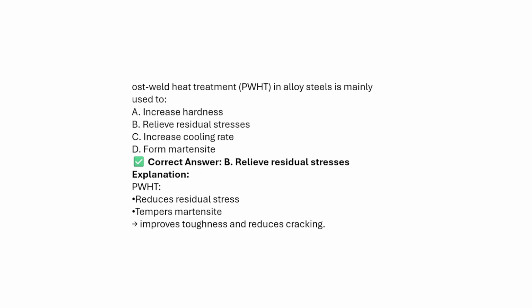Post weld heat treatment in alloy steel is mainly used to increase the hardness, reduce the residual stresses, increase the cooling rate, or form martensite. The answer will be to reduce the residual stresses. Post weld heat treatment reduces the residual stresses, tempers the martensite, improves the toughness and reduces the cracking. Okay.